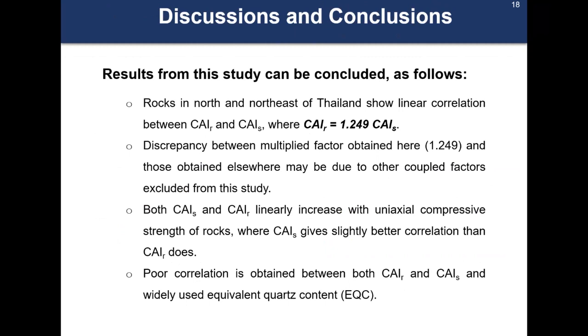The first, rocks in north and northeast of Thailand show linear correlation between CAIR and CAIS, where CAIR equals 1.249 CAIS. Difference between multiplied factors obtained here and those obtained elsewhere may be due to other couple factors not included from this study. Both CAIS and CAIR linearly increase with uniaxial compressive strength of rock, where CAIS gives slightly better correlation than CAIR does.